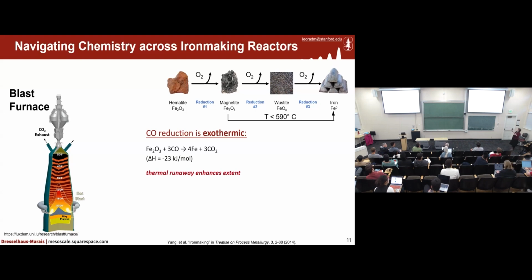So these massive, massive blast furnaces, what you're doing is really you're loading in alternating layers of iron oxides and coal. And what this does is we now blow hot air from the bottom, that creates activated CO that then, with a whole bunch of heat that's also generated by the coal, ultimately gives us this thermal runaway that enhances the extent of the reaction and makes the whole reactor be really in continuous flow. And these, as I mentioned before, can run for like 50 years before you have to service them the first time. They are a really, really good way for our country to have a really stable economy and infrastructure for producing technology.